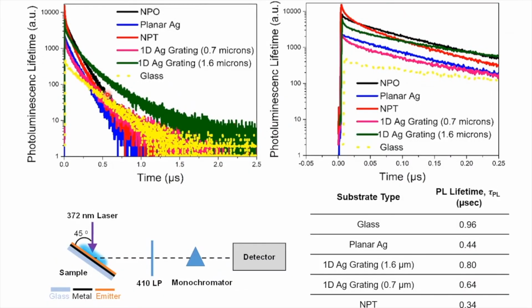We've clearly demonstrated improvements in the stability by coupling the phosphors to the metasurface. However, the mechanism is still a little bit in question, and we've been digging into this by taking transient photoluminescence lifetime and quantum efficiency measurements. You can see here, for example, compared to glass, there is a shortening of the lifetime anytime we put the phosphor on a metal surface.